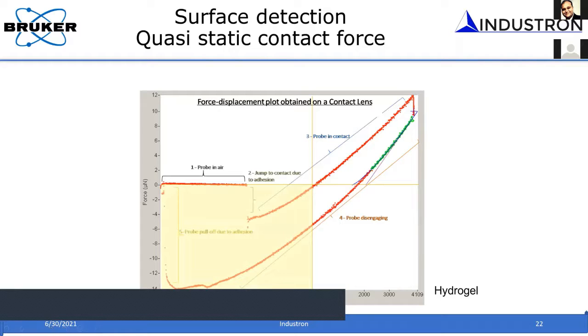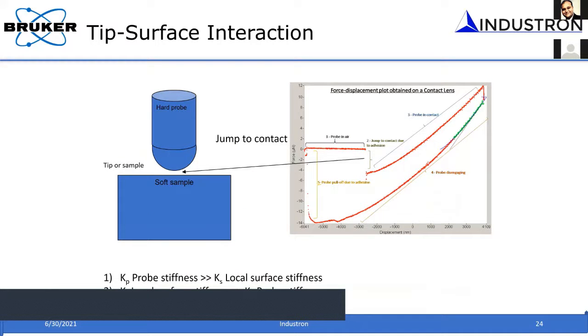But in fact, if you allow the measurement of the full interaction of the probe with the sample surface, you typically get a curve like this, very similar to what you normally get with an AFM, where the probe comes closer to the sample surface. As the probe comes closer, depending upon whether the probe has higher stiffness compared to the sample, or the sample has higher local stiffness compared to the probe, the probe may jump into the sample, or the sample may jump into the probe. That's why you get this jump to contact, due to the adhesion between the probe and the sample.